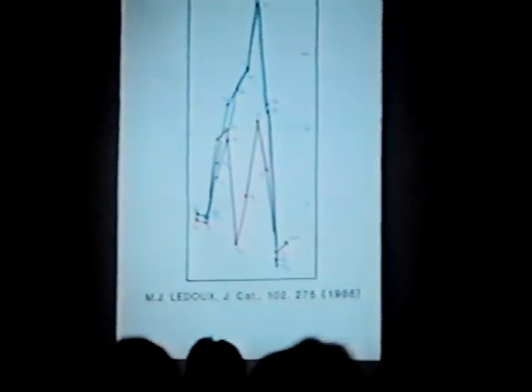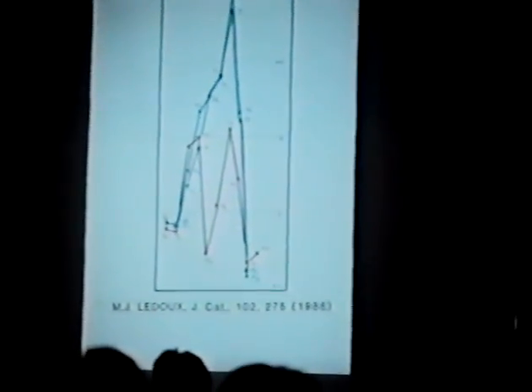I show this slide to indicate that many others have confirmed this periodic effect, and also that the periodic effects hold on most non-interactive supports like silica and carbon. But to my knowledge, to this day, when you go onto alumina, which is a very interactive support, these trends are masked. So that's another problem - when you're reading the literature and trying to relate the basic effects to what you're doing, you have to keep in mind that strongly interacting support will mask these effects. Again, this is related to the problem of understanding dispersion on alumina that I alluded to before.